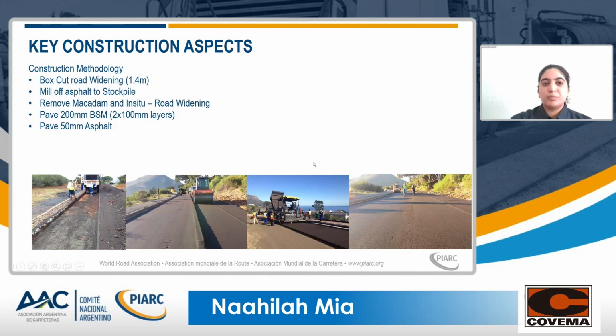So the construction was done as follows: we box cut the road widening, 1.4 meters, milled off the asphalt to the stockpile, removed the macadam, and then paved the BSM in 2 by 100 millimeter layers. And then on top of that, we had an AE2 binder asphalt of 50 millimeters.